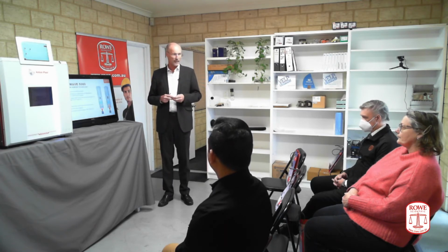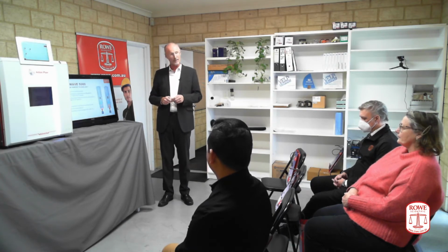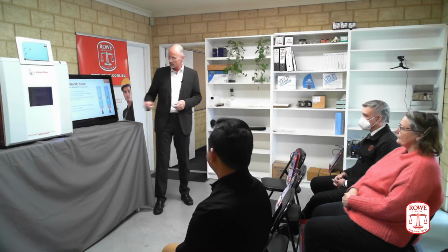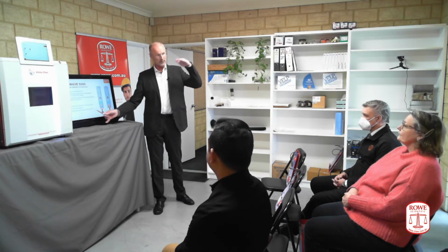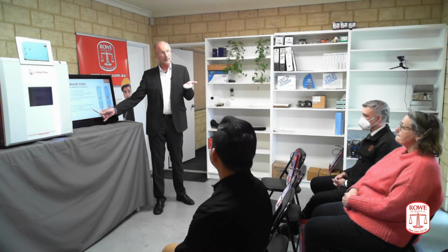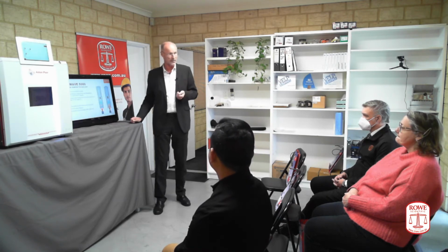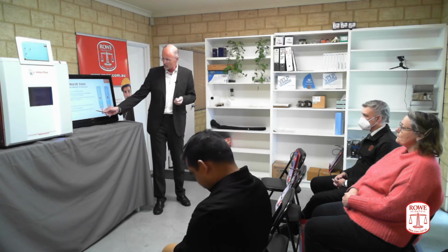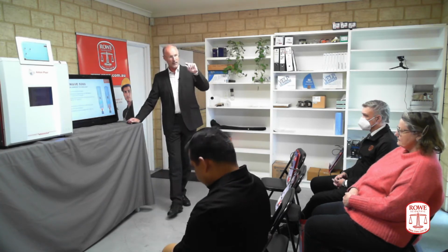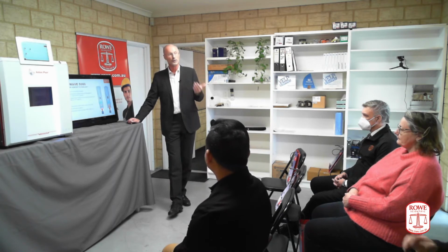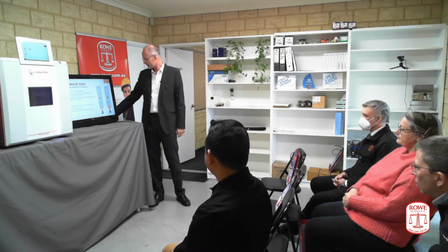What we further can do with all of our Anton Paar instruments, we can apply different temperature control strategies. Imagine you have a set of 24 vessels running there. They may have different reaction characteristics, and you can set the instrument either to control for the maximum temperature, the vessel that comes in highest, or you want to take all the vessels up to a defined minimum temperature. Then you set the control strategy to minimum, or, and this is what you do most of the time, you just take the average temperature of all vessels in the process. Depends on what your analytical requirement is.